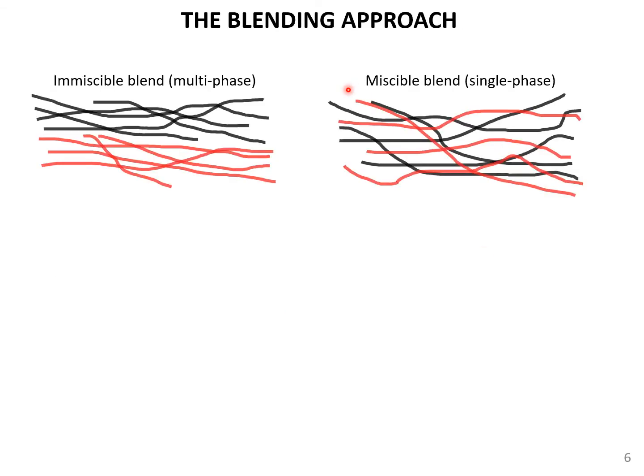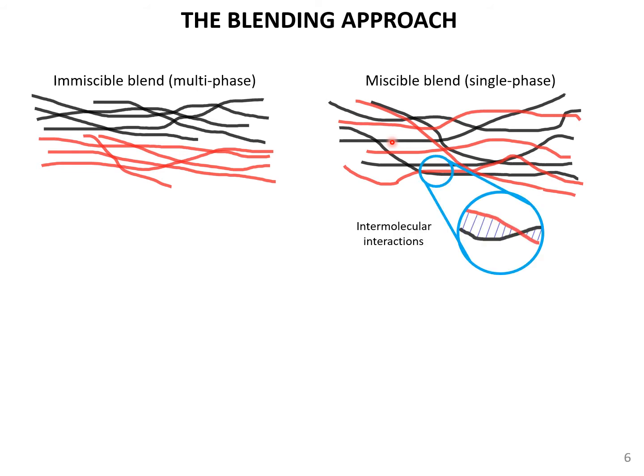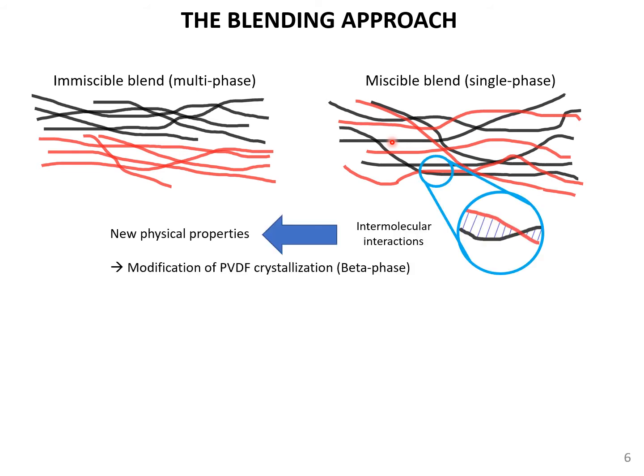So the most promising approach is blending. When you talk about blending, you have to consider immiscible blend or miscible blend. Most polymer blends are immiscible, so they don't have any affinity. But in the case of some miscible blends, you can have some affinity based on the fact that you have intermolecular interaction. Such a driving force can improve the physical properties, especially the PVDF crystallization, in order to obtain the beta phase.